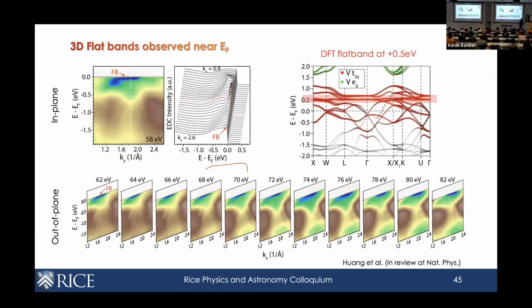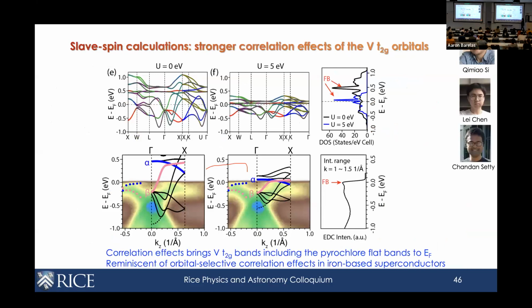But the problem is, if you go back to the DFT, you remember this flat band, according to this calculation, sits 0.5 electronvolts above the Fermi level. So Jian was like, what? Why is that? We had to think a little harder about why experimentally we can see it at the Fermi level. It turns out this is really interesting, because it reminded us of the story we worked on with the iron-based superconductors, which is that you also have to add correlation effects that were not taken into consideration in the DFT calculation.